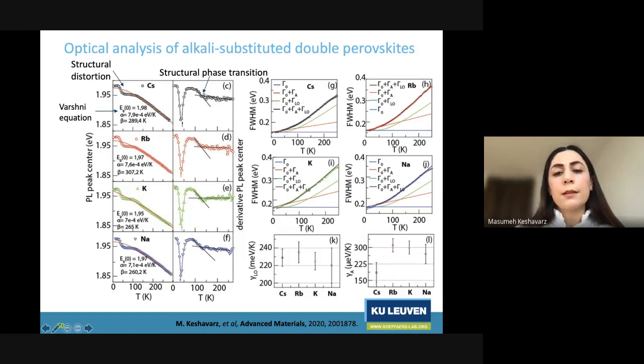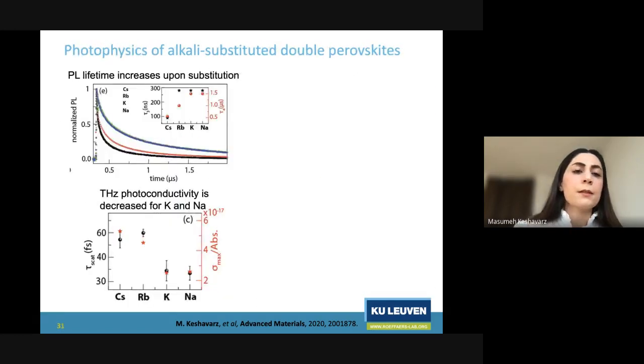So now let's look at their full width at half maximum as a function of temperature. The coupling constants are extracted through these measurements, and we see that it is more or less constant for the optical phonon scattering. However, the coupling constant for acoustic phonon scattering is increasing upon substitution, which we can attribute to the smaller ionic radius of the alkali metals which substitute the cesium. And that we confirmed through high resolution XRD measurements.